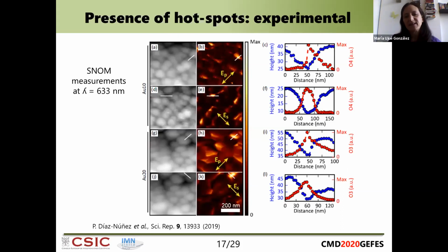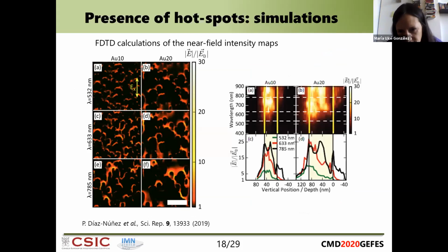We also have some simulations for the vertical case, where you could see also that the light is concentrated around, or maybe it's there. Yeah, here you can see, this will be the width of the nanocolumns. That will be the substrate. That is nothing, but you see the light is concentrated here, and then it goes down. So you will still have enhancement around 20, 30 nanometers from the surface.